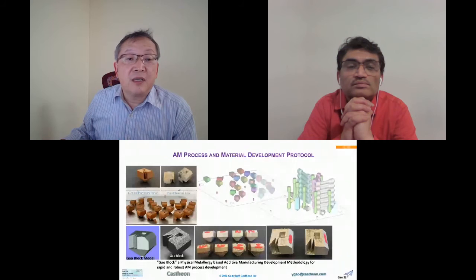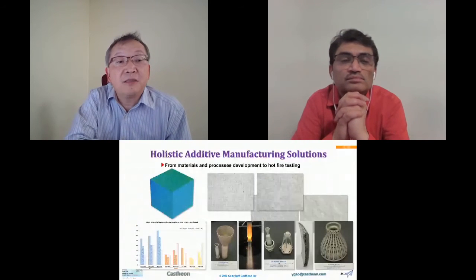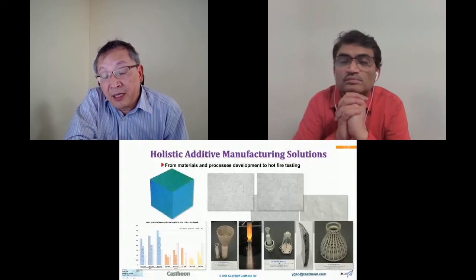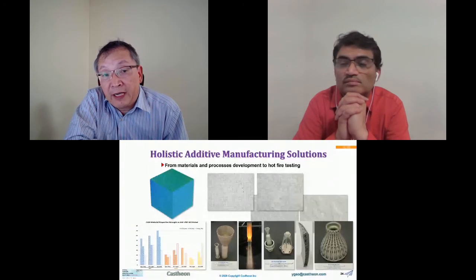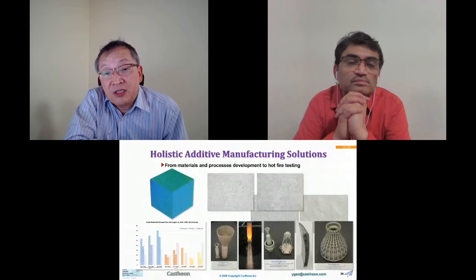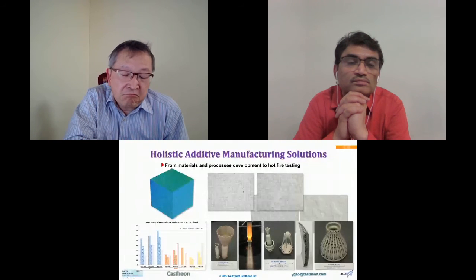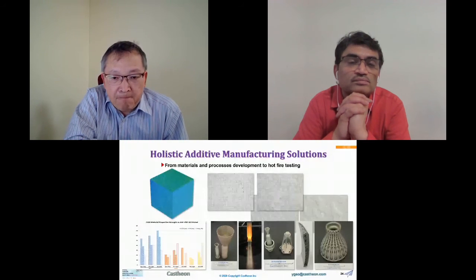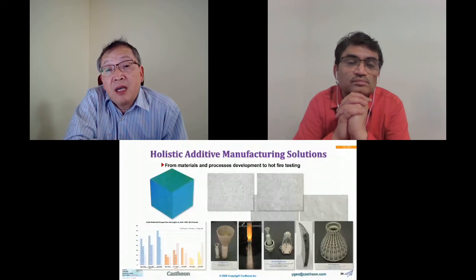Now going back to the high temperature applications, right? Previously I mentioned on the Haynes 230, we were able to get a far stronger and far higher temperature capable Haynes 230, just because we control the carbon and the tungsten and retain them in solid solution. So in the metal world, it's all about how you play with the solid solution. And once you can make solid solution in the net shape, you're the king.